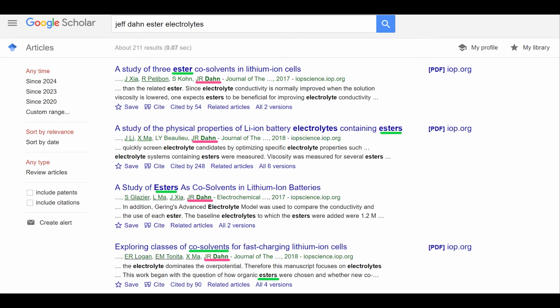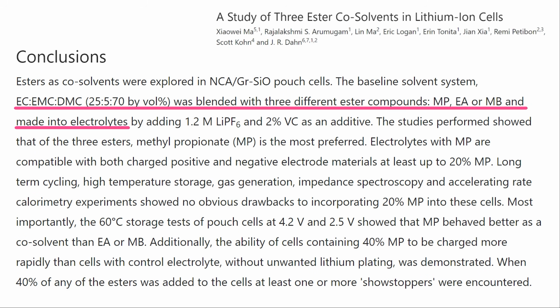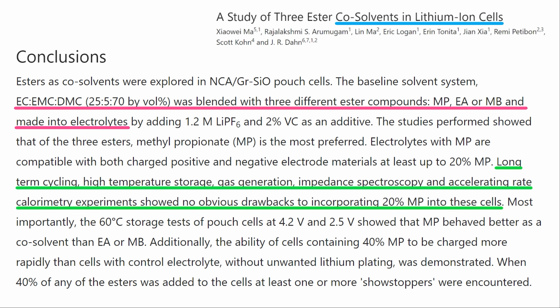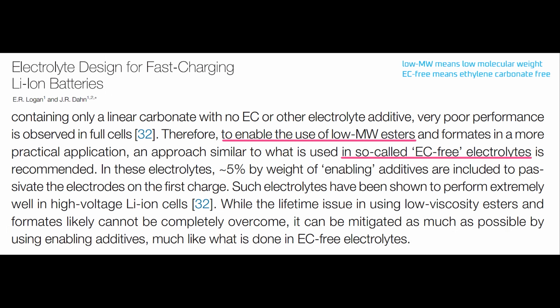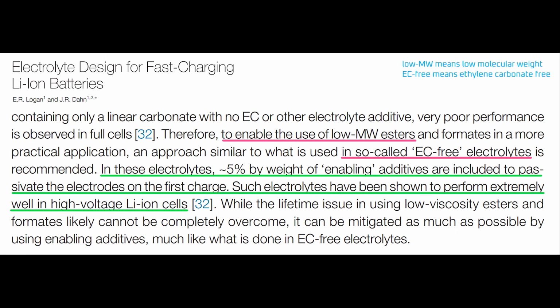Tesla's research partner, Jeff Dahn, has done a lot of research on esters, and he's suggested a couple of ways to improve their cycle life. The first is to use an electrolyte that contains both carbonate and ester-based solvents, which is called the co-solvent method. At an ester concentration of up to 20%, that results in faster charge rates without any apparent negative impacts to battery cycle life. The second option is to use a pure ester solvent, but to increase the additive concentration.